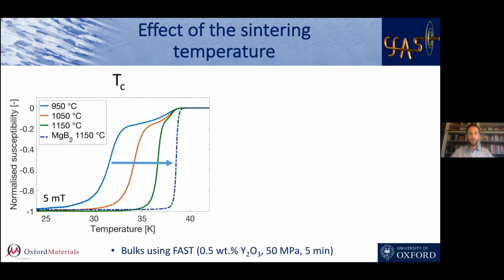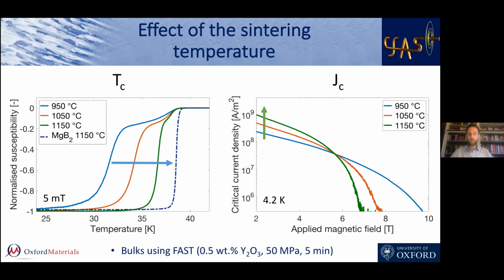And then slowly, as you process at higher temperature, you would recover that TC. And that's just because you annihilated those defects. But what was interesting was this part, the effect on JC. We saw that in simple MgB2, increasing the sintering temperature had only a positive effect that we can find here at low field, as shown by the green arrow.